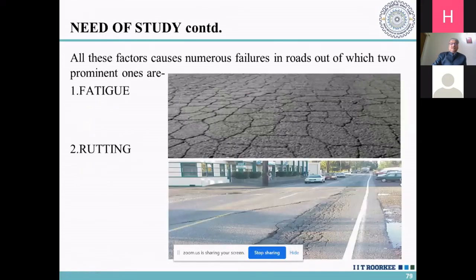So you can see here. Mainly we see that there are two things. One is the fatigue. This is the fatigue case. This is at the low temperature because of the movement of the vehicles. It is also known as crocodile cracking or map cracking or alligator cracking. And this is basically the rutting of the pavement. Rutting is taking place along the wheel path, the pavement is going down.